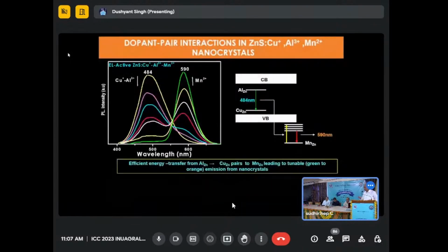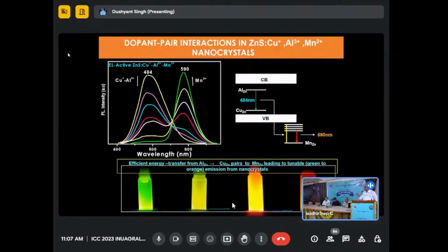Slow. Yeah. This is something very interesting. You see, we tried doping. One is manganese, another is aluminium. Now, what happens when you increase the quantity of manganese and reduce the quantity of aluminium? If you see the color change, it is going from green to orange. So now you can tune any color between green to orange by just varying the doping.